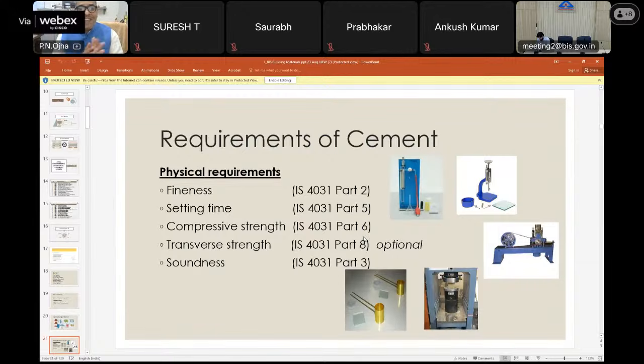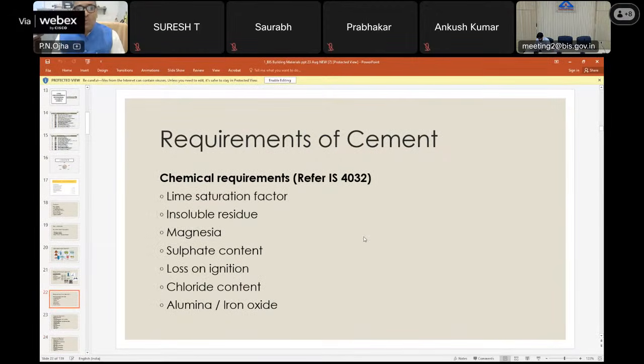And requirement of cement, as I said, fine physical property. These are the fineness, setting time, compressive strength, transverse strength, soundness. These are the test methods: IS 4031, part 2, part 5, part 6, part 8, part 3. The various parts of IS 4031 are available for physical property or mechanical property, both we can say. So the 4031 series is the standard test method standard for testing of physical properties of cement. And IS 4032 is the test method standard for testing of chemical properties of cement in terms of LSF, insoluble residue, magnesia, sulfate content, loss on ignition, chloride content, alumina, iron oxide, etc.